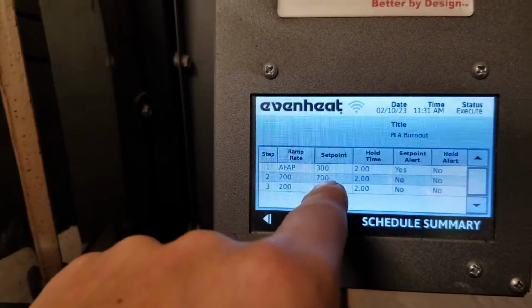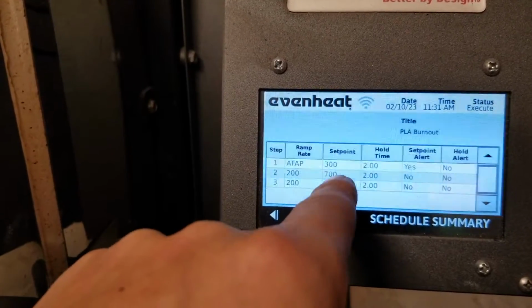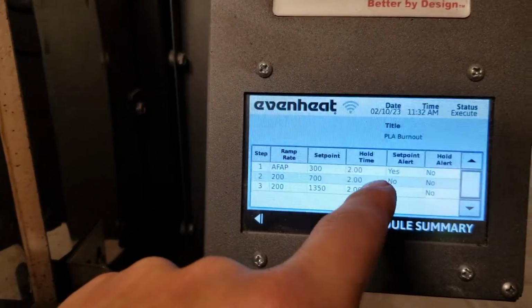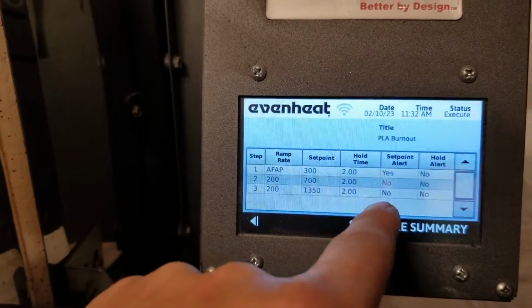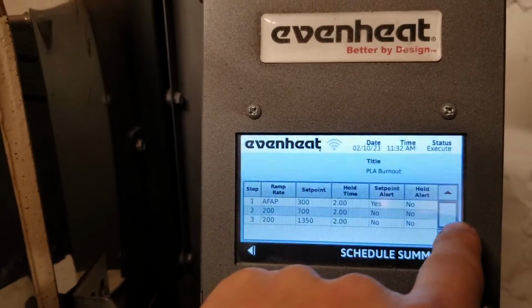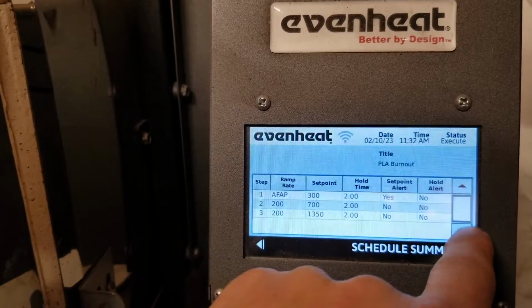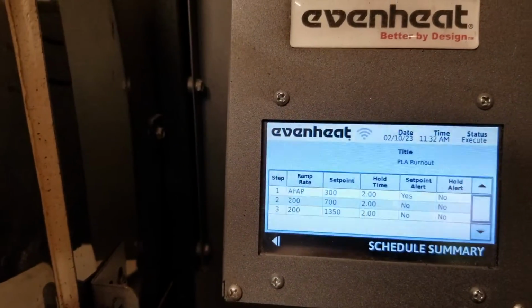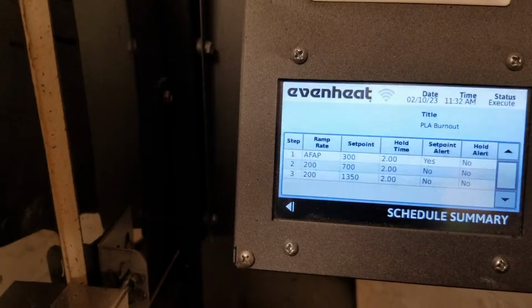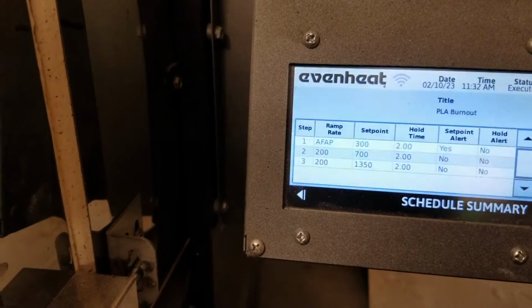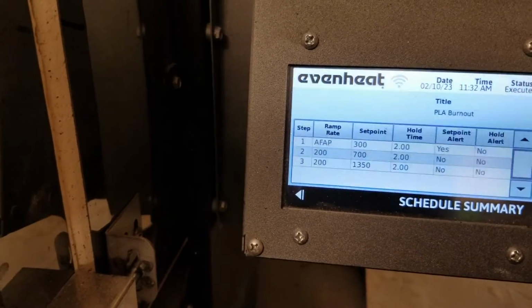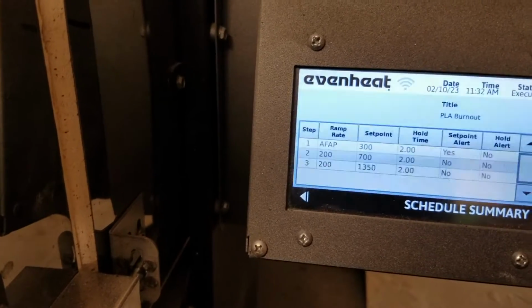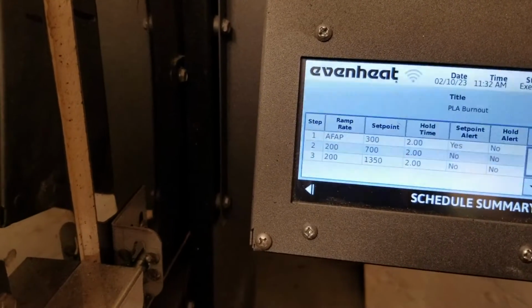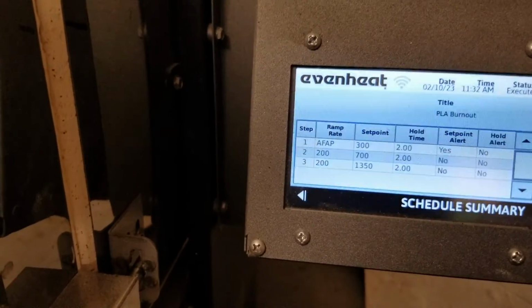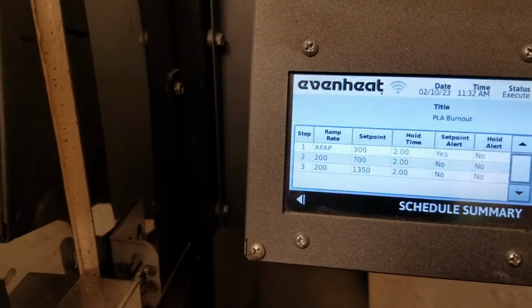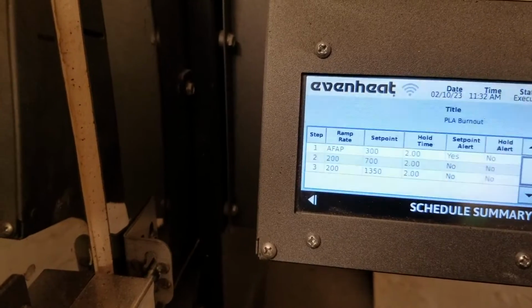Then it's gonna get to 700 degrees. And that's where we're gonna start to burn stuff out for 2 hours, and then 1350 for 2 hours. So that's gonna make sure that every last little bit is totally cooked out of there. And then it'll just cool back down, so that the total cycle is about 7 hours. So if your timing is good, when it's cooling down from that 1350, you'll be able to melt your metal and go to the casting machine.